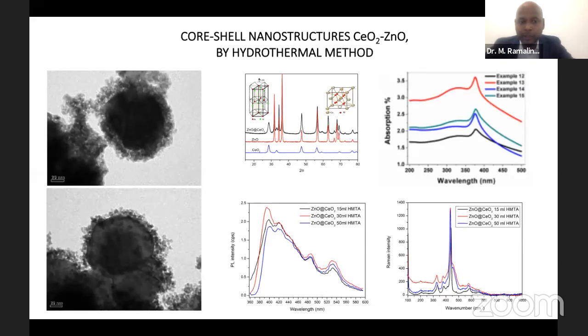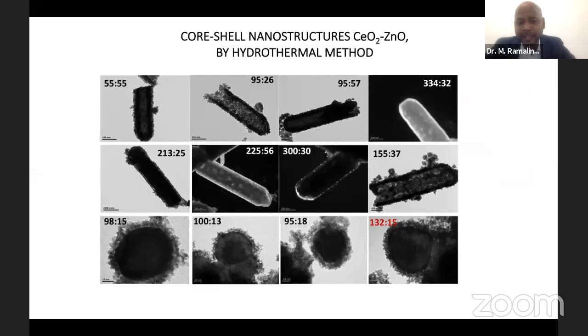The zinc oxide is a core, and cerium oxide is a shell. The fine particles of cerium oxide as a shell, and here also with different size and shape. Previously I showed them, and you can find spherical powders and rod-like powders also. Not only in the shape and form, also in the thickness of the core-shell we can modify.